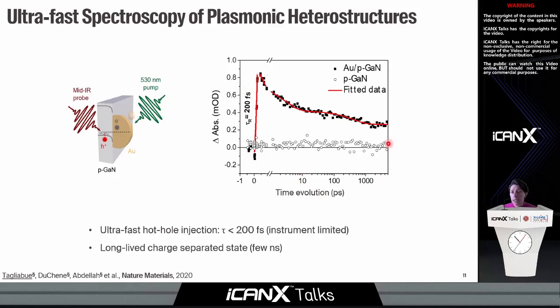Also, importantly, this experiment shows us that the presence of hot holes across the interface persists up to nanoseconds, which is very important information if we plan to apply this system for chemistry, because chemical reactions typically are slower, and therefore this ensures we have charges available for a longer time frame.